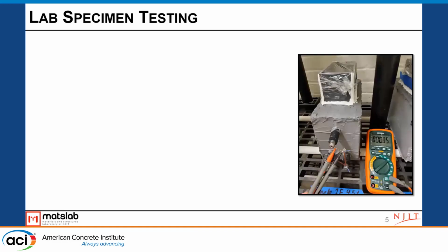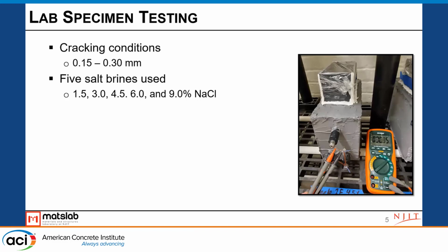So this test is based on the ASTM G109 method, and first we cracked the beam. So we get a bunch of different crack widths, and then we apply chloride ponding at the cracking surface. And we also want to study different brine concentrations at the cracking surface. In order to accelerate this corrosion test, we applied wet and drying cycles up to around 1 year. Each cycle is 14 days.